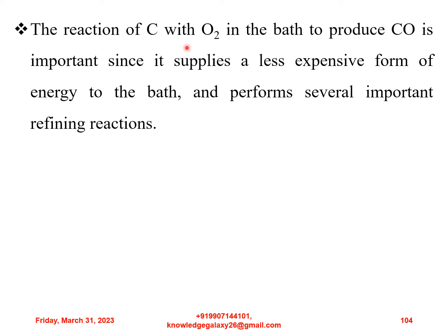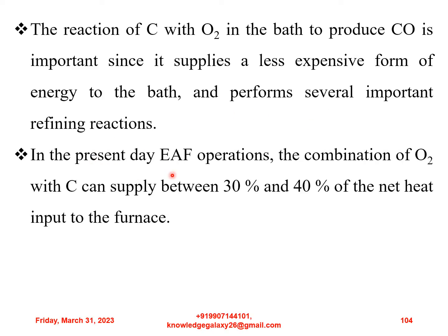The reaction of carbon with oxygen in the bath to produce carbon monoxide is important since it supplies a less expensive form of energy to the bath and performs several important refining reactions. In the present day electric arc furnace operations, the combination of oxygen with carbon can supply between 30 to 40% of the net heat input to the furnace.